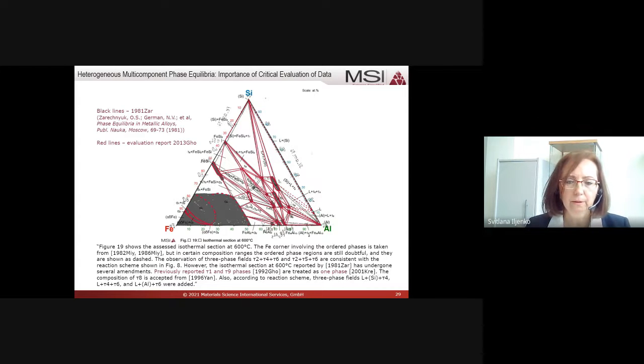Another example. Here, an interesting point was about the existence of previously reported tau 1 and tau 9 phases. These are ternary phases, which are traditionally called tau. These are this composition and this composition. Later, in the later work, it was found that in fact there are no two, this is only one phase. And respectively, the equilibria also have been changed. Now they are joined in one, respectively some 2 and 3 phase fields have disappeared from the diagram.